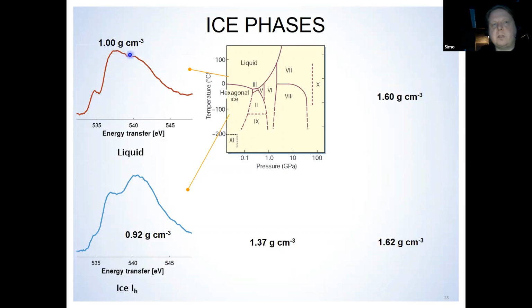and the post-edge structure. In contrast, ice 1 hexagonal has a much lower pre-peak than the liquid water, because basically it has less broken hydrogen bonds, ideally none. And then you have a strong peak here at the post edge because it has a fully tetrahedral coordination.